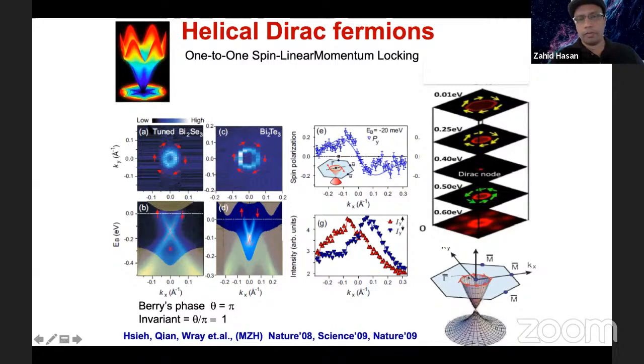associated with a branch. So when you look at the full Fermi surface, we see there's a spin winding. Each momentum is locked to a spin state. For example, one way to read this is that if K plus is spin down, then K minus would be up. So in real space, the picture is kind of like that. And then how do we know this is topological? Meaning that the full picture has to be gapless everywhere in the bulk. The surface has to be gapless everywhere in the bulk gap, in the energy momentum spectrum.